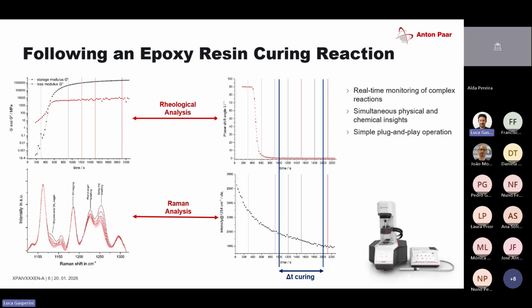So how does the setup actually look like? You have this Raman fiber probe which you put at the bottom of the instrument, and instead of a stainless steel plate, you use a quartz plate. So during the rheological measurement, you can actually get a chemical insight. And especially for more complex curing processes, this can be very, very interesting.